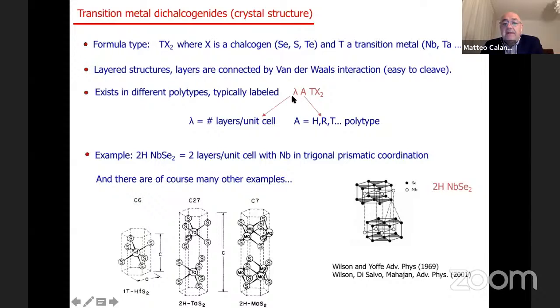These polytypes are labeled with the following formula: lambda A TX2. TX2 is the stoichiometry. Lambda is a number that tells you how many layers you have per cell. So if this is a 2, for example, like 2H niobium diselenide that you see here, then there are 2 trilayers per cell. And A is a letter that labels a different kind of polytype: H, R, and T. These H, R, and T do not mean hexagonal, rhombohedral, or something else, but are simply letters. H means that the niobium is in trigonal prismatic coordination. T means that it is in octahedral coordination. R means that it is in trigonal prismatic coordination, plus a different stacking between the layers, and so on.